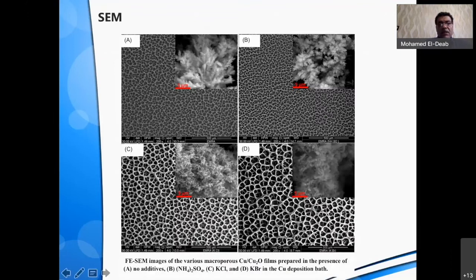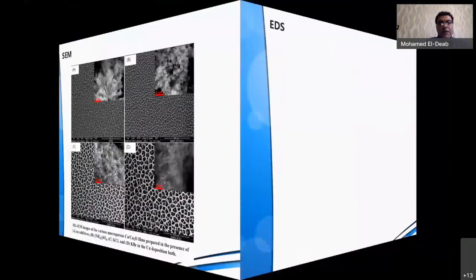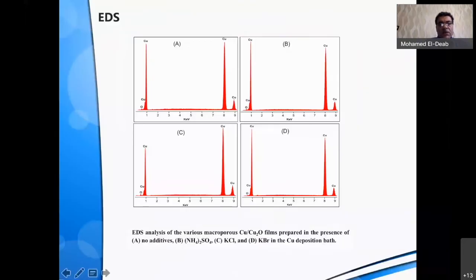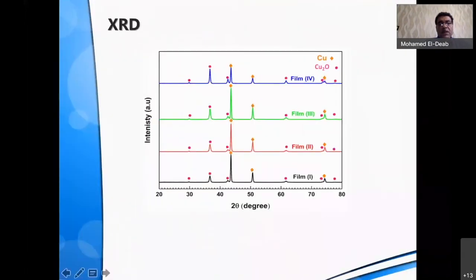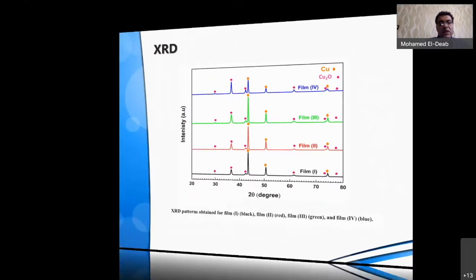Images are more or less similar, but the fine structure is a little bit different, and we cannot get any information from here except that we have some porous foam layer formed on the copper substrate, the planar copper substrate, and the EDX also confirms that we have copper and a little bit of oxygen on the top of the copper foil. XRD patterns are more or less similar, except for the relative enrichment of copper to copper oxide ratios, which is of insignificant effect on the catalytic activity, as we will see later on.